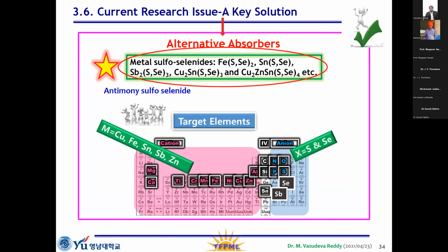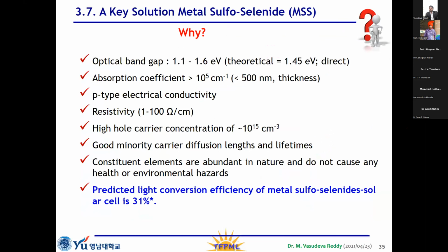So what is the reason why we should focus on these two materials? The optical band gap is around 1 to 1.6 electron volts, and theoretically ideally we need just 1.45 electron volt for the application. And the absorption is 10^5 per centimeter. This is really high, and we need just 500 nanometers. The p-type conductivity is also important, and the resistivity of these layers is around 1 to 100 ohm centimeter, with reasonably sufficient hole carrier concentration. Also a good minority carrier diffusion length and lifetime.